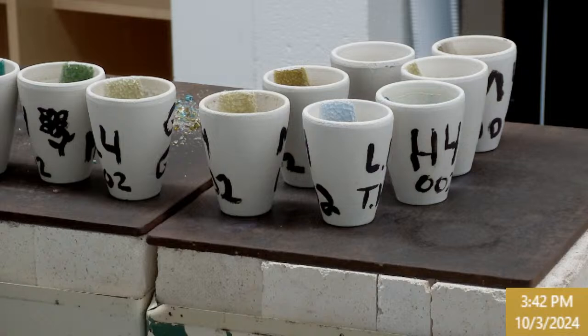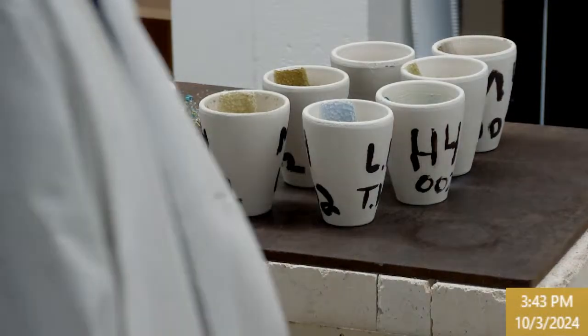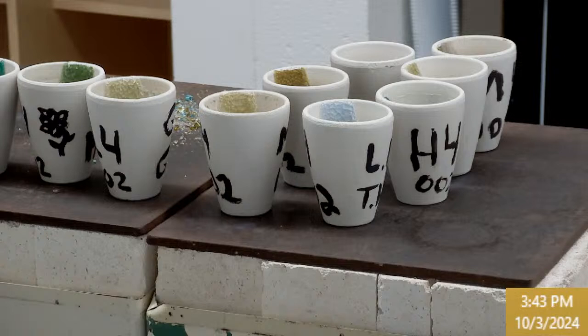Aluminum tightens it up, often makes it shatter. Potassium isn't as good of a flux, and it makes these tight discs that then shatter. Lithium destroys my furnaces because it's so small it evaporates and fluxes the wall of my furnace. And so I have not used lithium on this one at all yet. But if you look at the top, you can see that she's sagging.